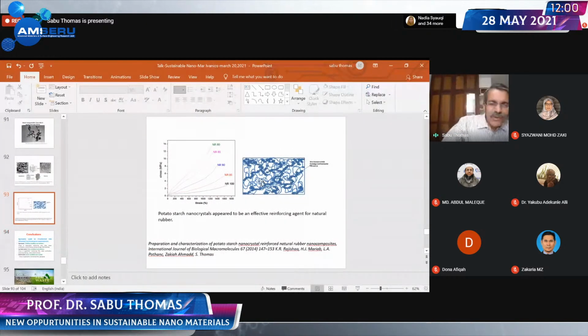And a PhD student of mine put these nanocrystals of starch into natural rubber latex. And you can see by increasing the concentration of nanocrystals, we got a very high modulus material. Natural rubber became a high modulus material. And she made a beautiful cartoon. You can see that these are the macromolecules of natural rubber, and nanocrystals of starch made a network. And this network immobilized natural rubber chains. That is why you have an increase in modulus.